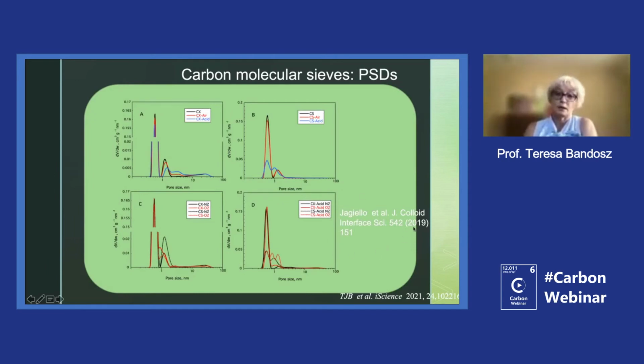In that work, in fact, it was presented that if there are no specific interactions, the distributions should be similar. So similar distributions were expected, but not exactly the same distributions were obtained. Here you can see for the initial sieves, the red lines represent the distribution from oxygen, and especially for the sieve which was modified with acid, even though the sizes might be considered in a similar range, we have some more heterogeneity.